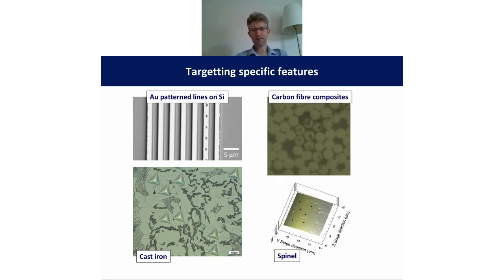So as well as these grid indentation experiments, we can also target specific features of interest on our material. So we can, for example, accurately place indentations to really a couple of nanometers precision. In this example, this is from MIT, and this is actually nearly 19 years old now. So we've had this precision, and we've been a leader in this industry for a long time. You can see how we can put these indentations right in the middle of these soft pattern lines on a silicon substrate for a MEMS application.